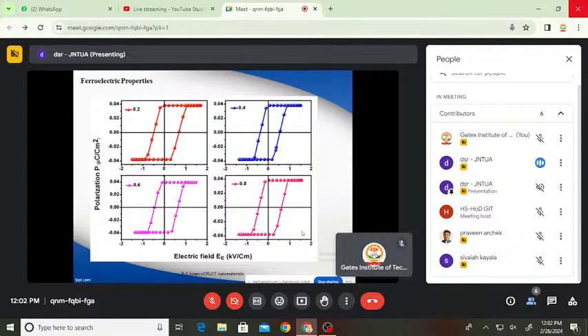Similarly, the frequency dependence of AC conductivity is also investigated. For Z equal to 0.8, it is found to be around 7.5 times 10 to the power of minus 6 Siemens per centimeter. From the PE loops of 0.2 to 0.8 contents, they exhibited well-defined hysteresis loops. However, these loops are distorted into banana shape, and further the leakage current is created because of the formed oxygen vacancies on the upper surface of the grains, in spite of polarization.